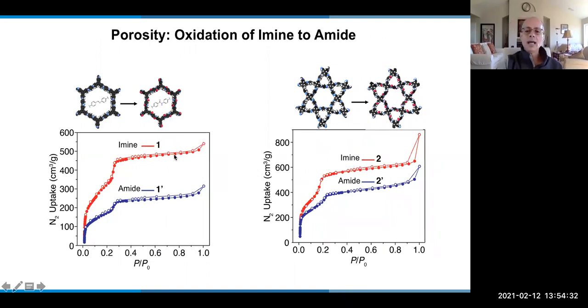And we study their porosity. And you can see here that the imine and the amide porosity differ. We think we're not evacuating the pores as well, but the material is still porous. So we are still working more on activating the material, trying to find those perfect conditions that remove everything that is in the pores. But we have other examples that we published where the porosity is not affected at all. But in this particular reaction, the amide reaction, they seem to be affected because the amide attracts more, we believe, more water, and these waters are very hard to remove, and therefore the slightly lower porosity.